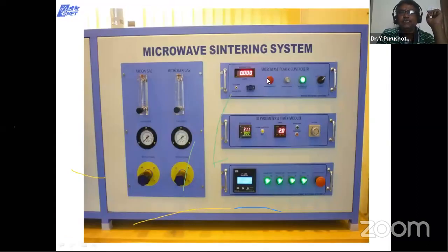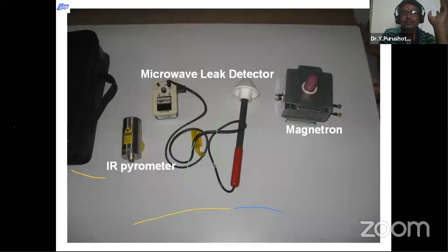And this is the microwave power controller, and these are the IR pyrometer and temperature display. We can program the PID controller, so as per our requirement, one can do sintering. And before starting, we have to check with a micro leak detector whether any leakages are there, because exposure to microwaves for a longer duration is not good for our health. So this is the magnetron and this is the pyrometer.